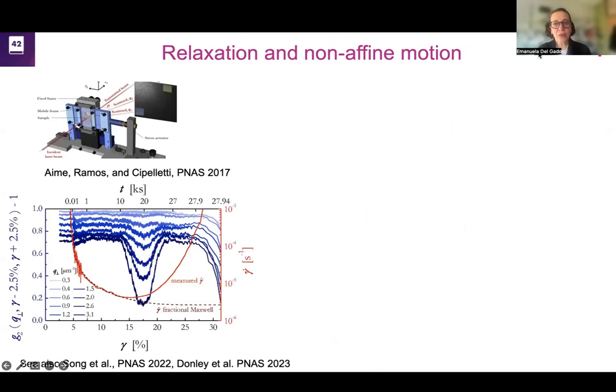So at this point, it has emerged as a very important question to ask what is actually the microscopic dynamics of the system under load in more detail. And this has now become possible thanks to experiments like the ones developed, for example, in the group of Luca Cipelletti. This is by Luca Cipelletti, Lorenzo Ramos, and Stefano Aime, who built this shear cell, which combines the possibility of doing stress-imposed studies with scattering. And so you can measure the rheological response, and then you can measure the microscopic dynamics. In particular, the way the cell is set up is to measure the displacement of the particles that does not simply follow the deformation.